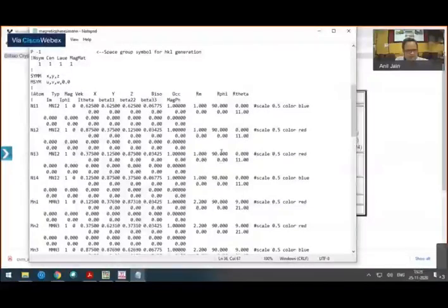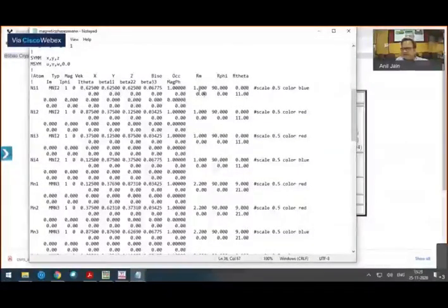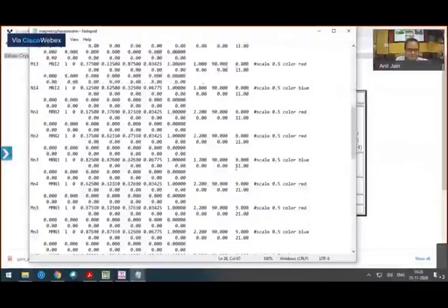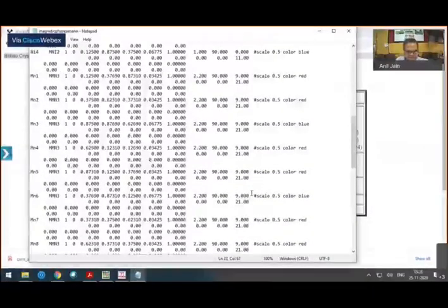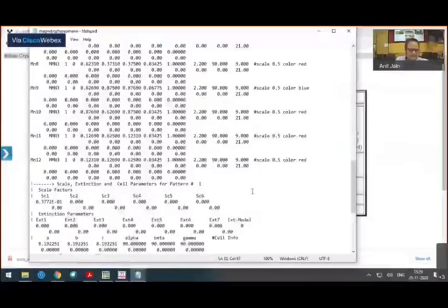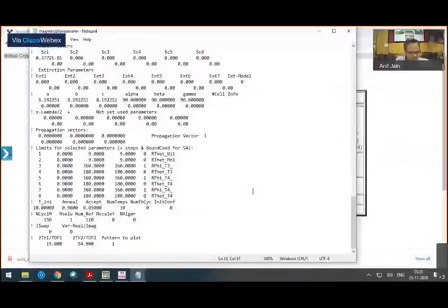So in this case you can easily put a constraint on the length, meaning the magnitude of the moment. And then for the phi and theta parameters, either you can restrict them or you can leave them free. Then you can run this simulated annealing file and try to see what kind of magnetic structure it gives.